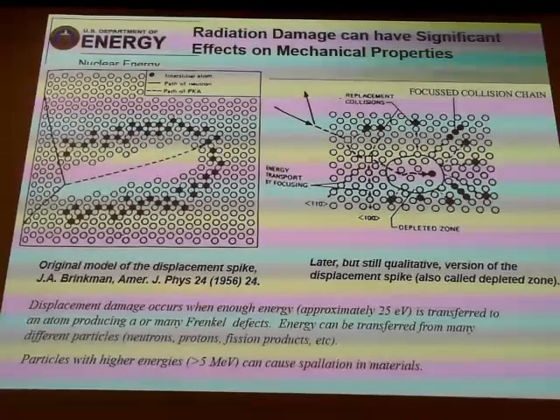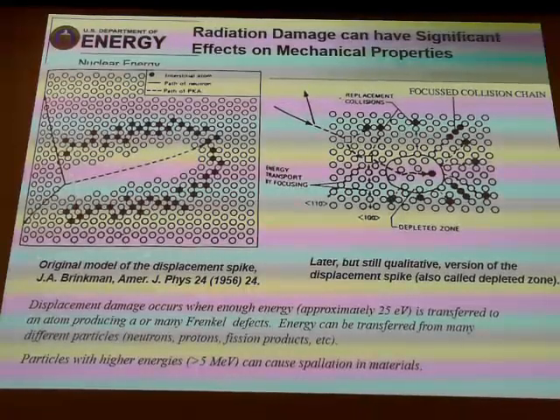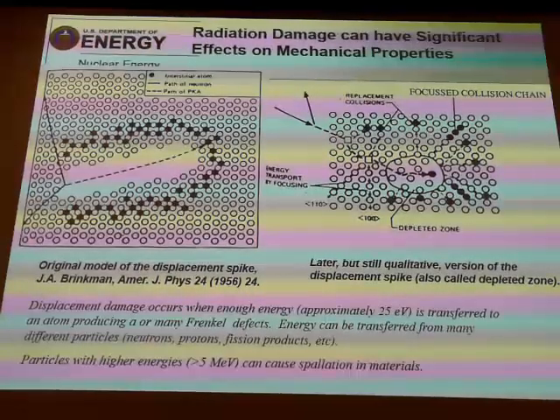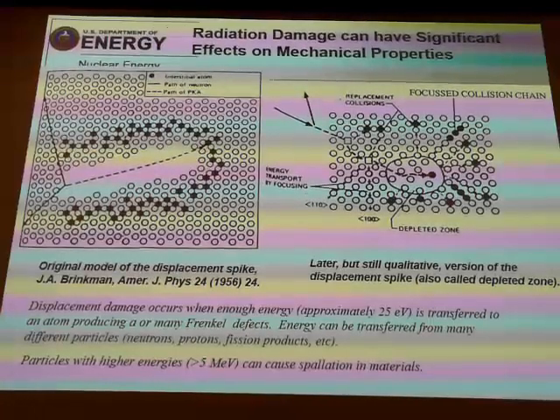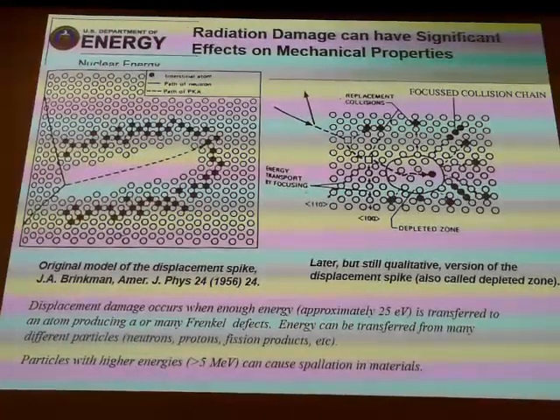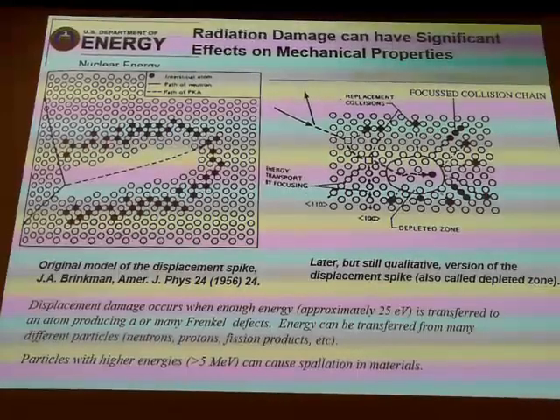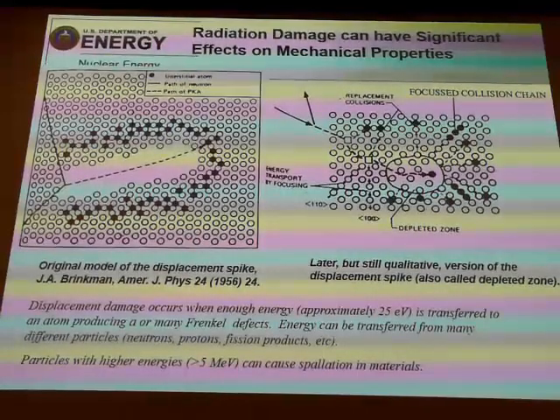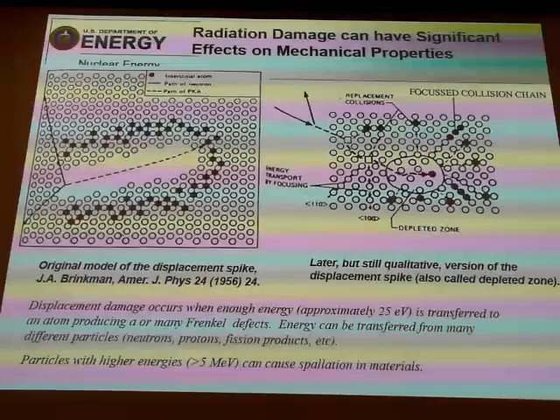So I think most people know this background, but clearly when a high energy particle comes into a crystalline material, it can interact with the atoms and cause a large cascade, transferring the energy into the atoms and the atom structure, and then following that, making in the cascade, you have of course, a very large area of vacancies and interstitials. But then, of course, after that displacement spike relaxes, then you end up with a large number of vacancies as well as some interstitials left in the material.